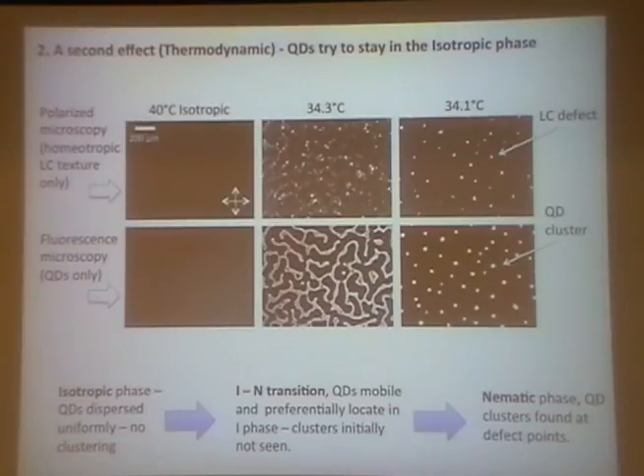So we take the sample, say we have a quantum dot cluster, and then we reheat. After some time, you start to see a halo around the cluster. So it's a much slower process. Coming apart is a much slower process than this formation process. When we go from isotropic to nematic, they get pushed together into a cluster. But when we reheat, they only diffuse out very slowly.